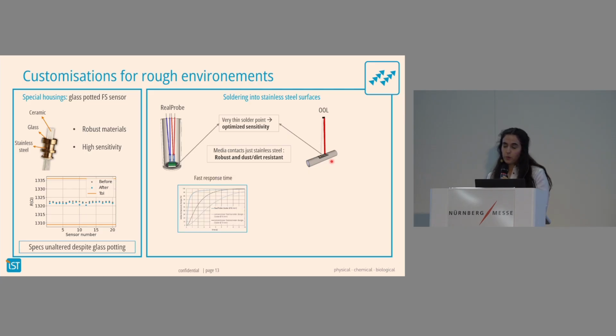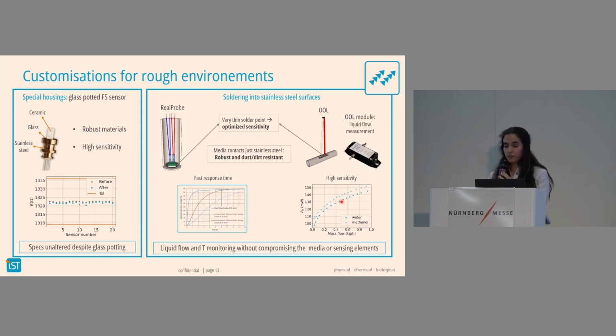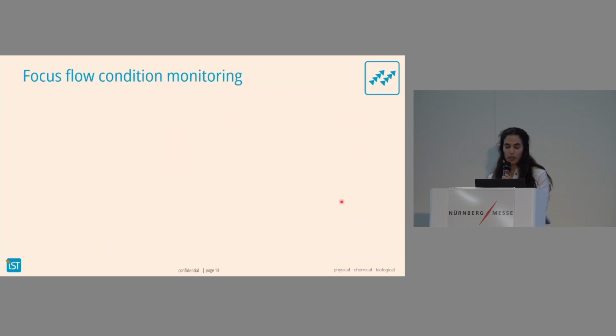And what we are showing here is that, with this extra material from stainless steel and soldering, the response time is not affected, so it's still quite fast. And the sensors still have extremely high sensitivity because it's possible to detect very small flows and to differentiate between them. Just as a small hint, this OOL solution we also offer as an OOL module that has a direct flow output. And now coming into a little bit more focus on the flow condition monitoring.